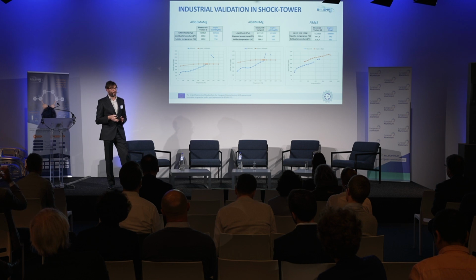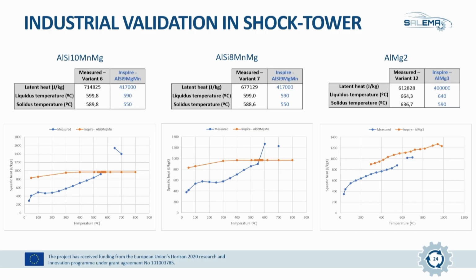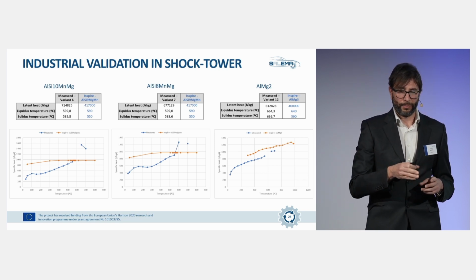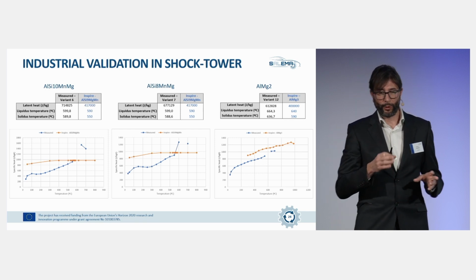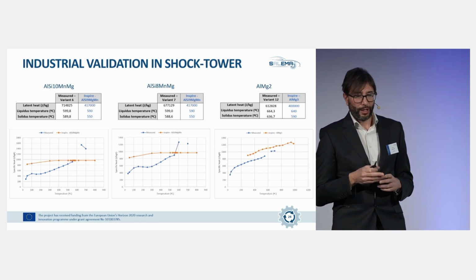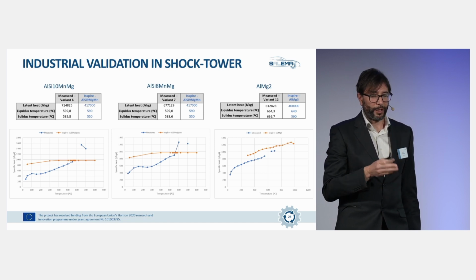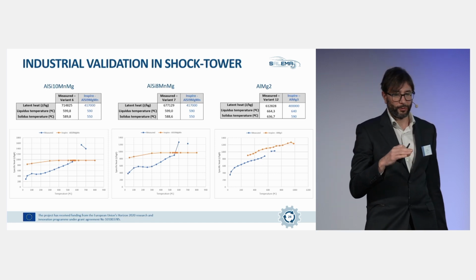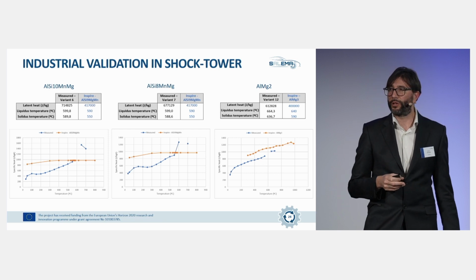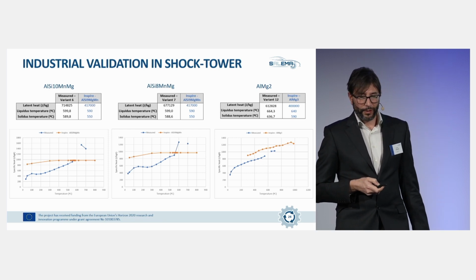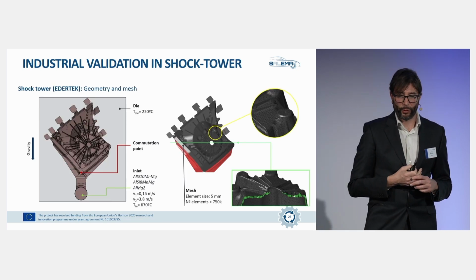From here, in order to move to the new alloys, the first thing we did was to characterize the thermal and physical properties of the alloys required by simulation software in order to simulate the filling and the solidification of these new alloys with the shock tower geometry. So we did it for the 3 alloy variants we were going to test with this alloy, and we measured the required properties, latent heat, liquidus and solidus temperature, and also the specific heat at different temperatures. Okay, and with this input, we went to simulation.